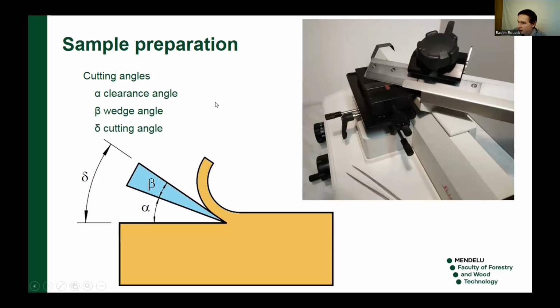During cutting, there are some angles, like shown on this picture. I use this Leica microtome. There are some possibilities to set the angles, and I will show you. If you have a big cutting angle, which is delta here, then the shaving is more bent, more pushed or compressed, and there is a higher possibility to damage the surface. So the cutting angle or the clearance angle should be very low, very small to get good results.